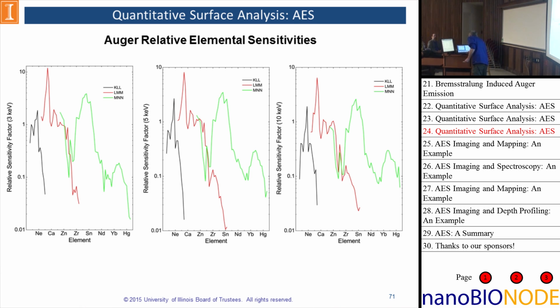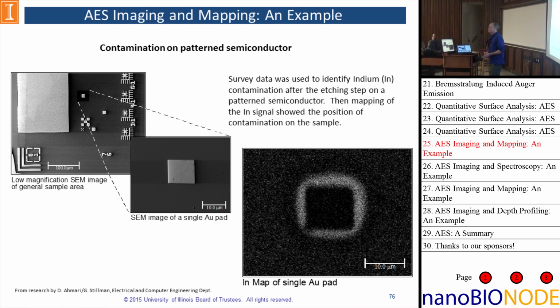Okay, let's jump up to some other capabilities. Because the Auger behaves like an SEM, you can use it as an SEM. Here we have an SEM image of a sample, and they're interested in studying the etching of indium from this patterned sample. And so they're concerned about what the edges of the pads look like.